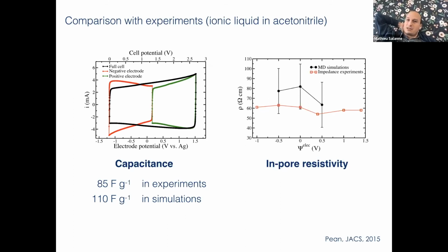And then we also checked the dynamics, because this is important since we are looking at power devices. So for this, what we did is to compute the electrical conductivity of the liquid inside the pores. And this can be compared with some impedance measurements that were also made on the same systems. And here you see that the error is also of 25%, 80 instead of 60, that's on the right. So when we know the accuracy of classical molecular dynamics for transport in general, we can say that this is a good agreement, and so that the dynamics of the system is well reproduced.